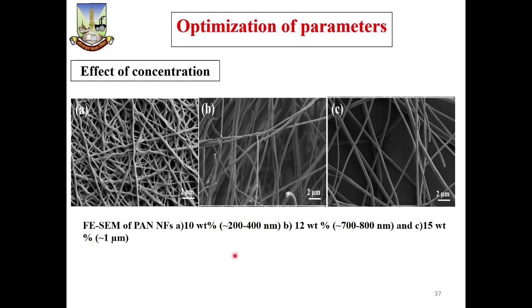Therefore, it has been suggested that mild, moderate viscosity is an important parameter that will give a very low size of the nanofiber, and it is suggested that a solution viscosity of 10 weight percent is sufficient to draw the fiber of 200 to 400 nanometer.